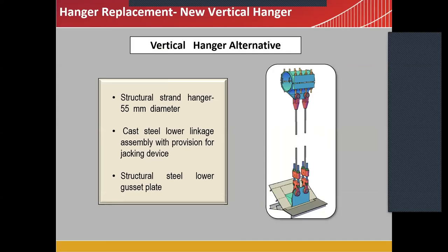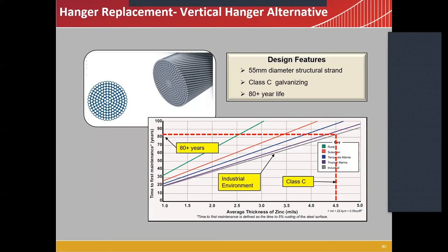In the vertical hanger alternate, we use double structural strand hangers instead of wire ropes. Those were 55 millimeter diameter, with a cast steel lower linkage assembly with provision for a jacking device, and structural steel lower gusset plates. Design was for 80 plus years of life. Therefore, the outer layers of the wires received Class C galvanizing.